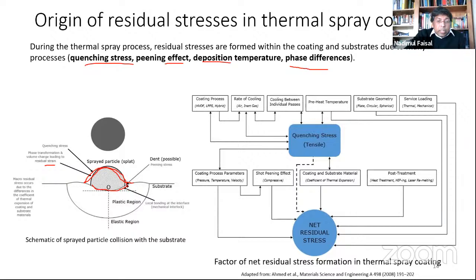And then based on the velocity and temperature, the local bonding will happen with the substrate. So a lot of events are happening in this small volume, and that is very important. A lot of data is getting generated. And then if you build up layer by layer, powder particle by particle, you can end up getting a thick coating, and then eventually you will get a macro residual stress. Right, so that is a bit complex.